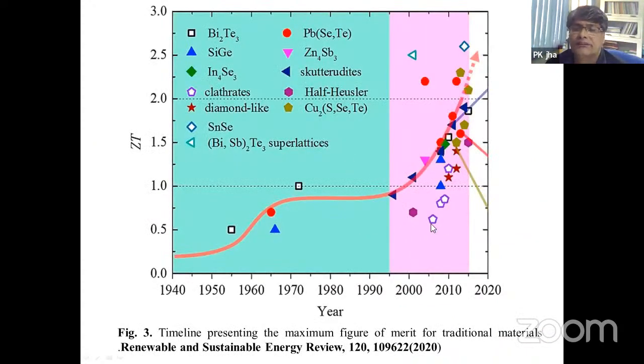In the last few years, you can see that though it started long back, maybe in the 1950s, with a very popular material Bi2Te3, with ZT having only 0.5, in this region, that is 1995 to 2015, most of the materials have been researched, and it is found that a large number of materials have the ZT between 1 to 2. Some materials, of course, have higher values also. In the beginning, it was of interest to have the ZT value up to 1, right? But that has been surpassed long ago, and now people are trying to have the ZT value more than 2, right? And that is the aim.